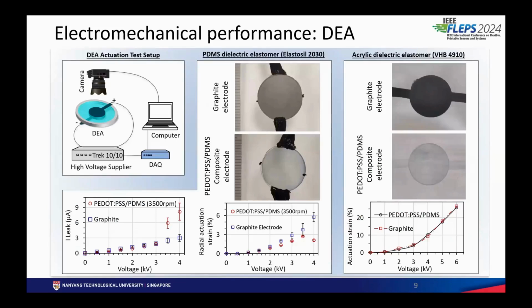And going to the basic evaluation of dielectric elastomers made with this ink. Conventionally, dielectric elastomers were made using either carbon grease or graphite powders. So this is the most widely used electrode for dielectric elastomer actuators. And we have compared our ink with this electrode.